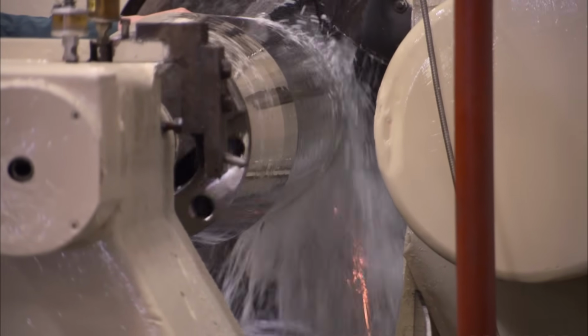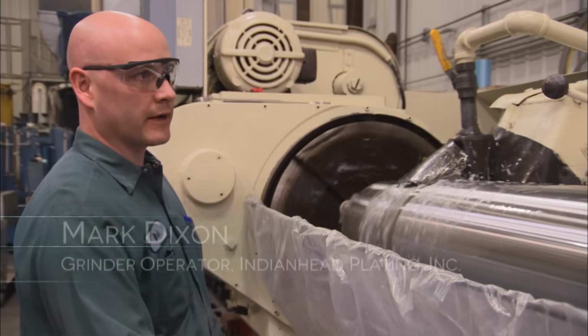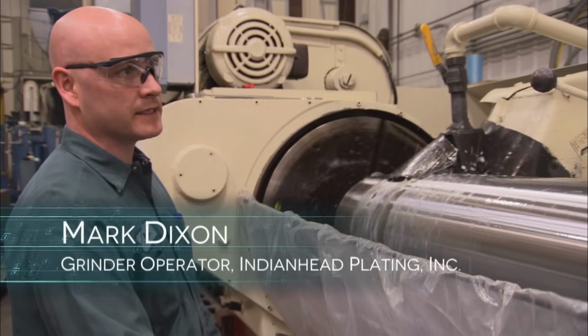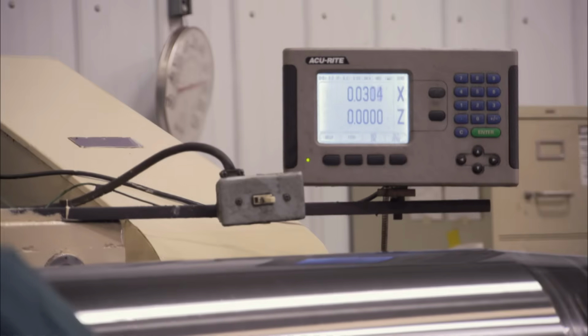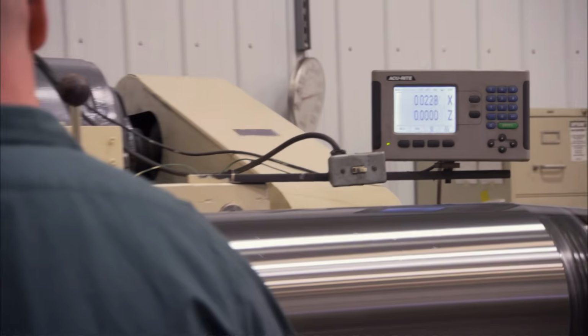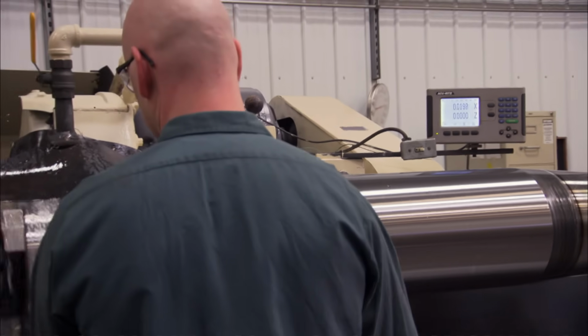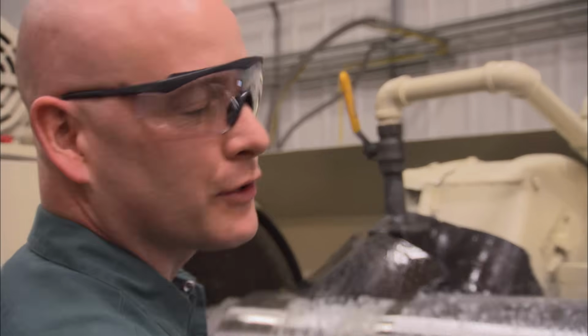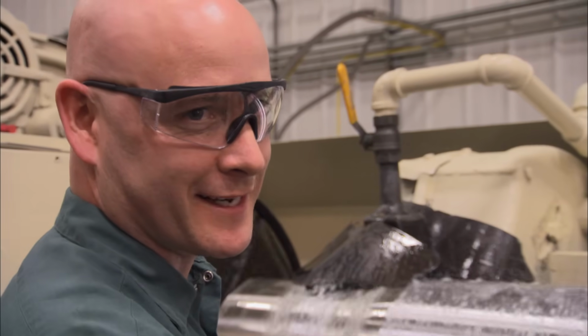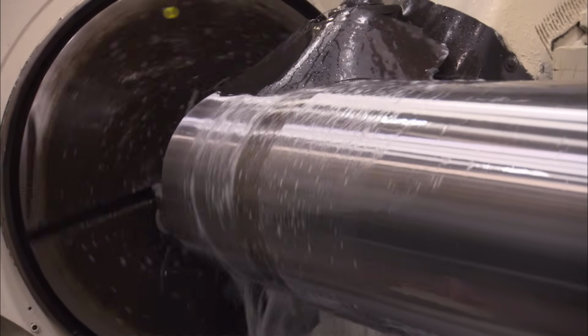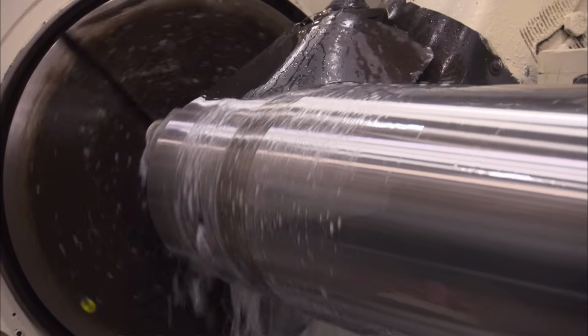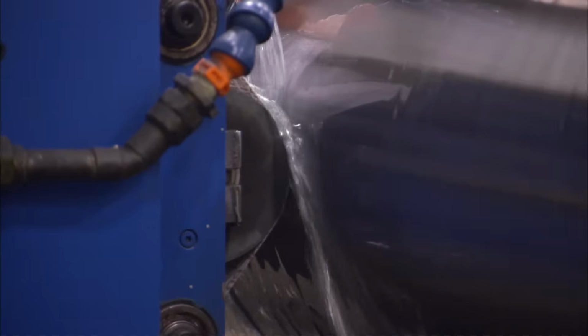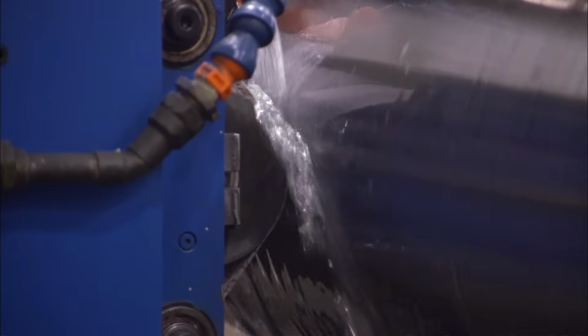Chromium has great wearability, which means it doesn't scratch or deform over time. This is important when you need to have a perfect fit between parts. So right now I have to bring this down to a specific size. In this situation we have a 3 thousandths tolerance. So right now I have 4 thousandths to go after I measured it. Your hair is approximately 3 thousandths thick. So I have to bring this down to 0.004. Right now I'm plunge grinding, just going straight down onto the part.